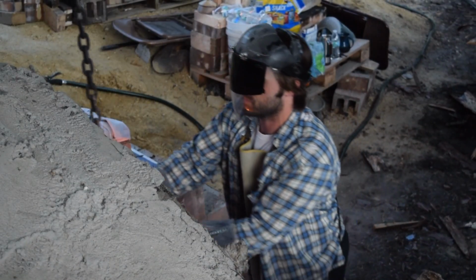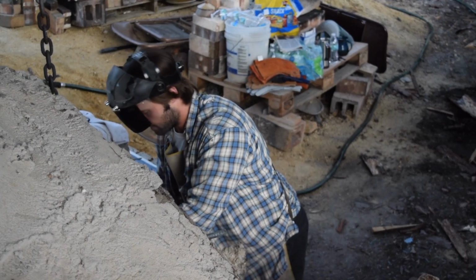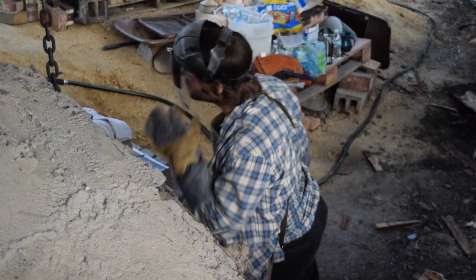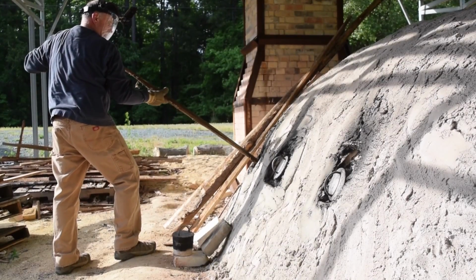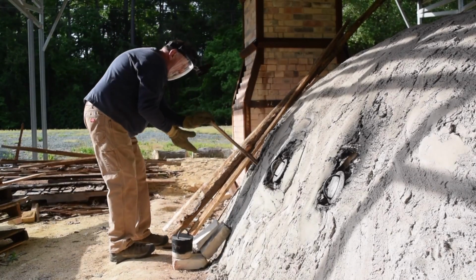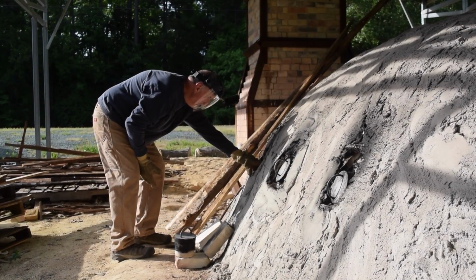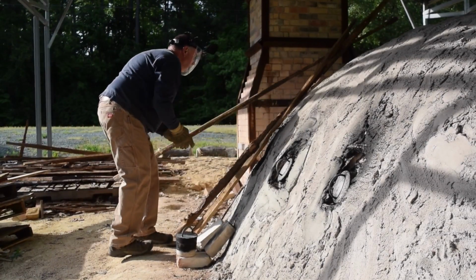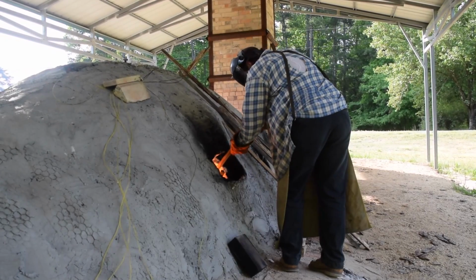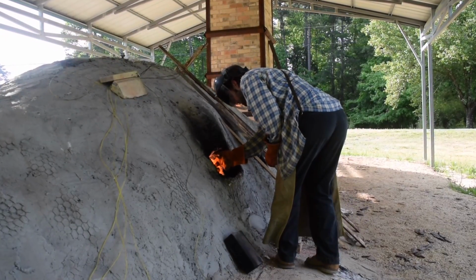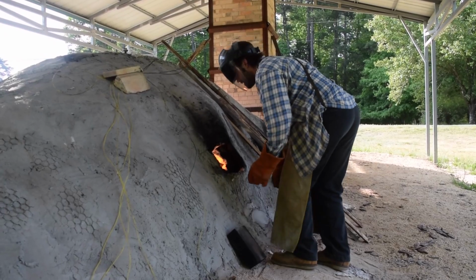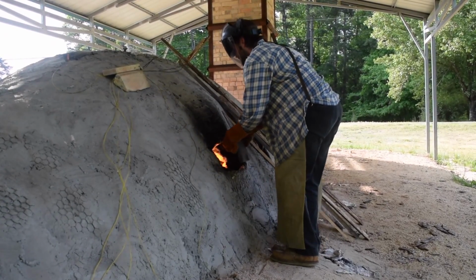Here, like I was talking about before, is video of Bob stoking the back of the kiln, trying to get that heat to the very back. We could have 2350 degrees in the front, and then all the way in the back only have about 2100 to 2200 degrees. It's very important to even out the front to the back so that we get even heating among all of the pots.